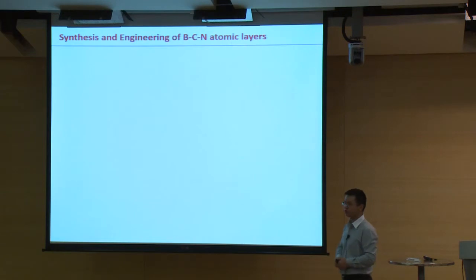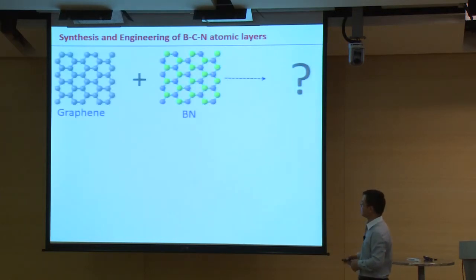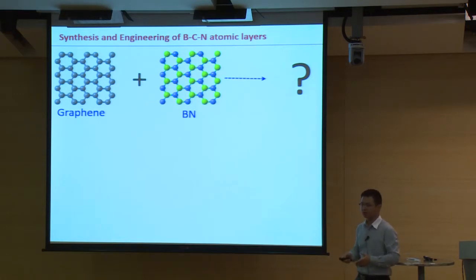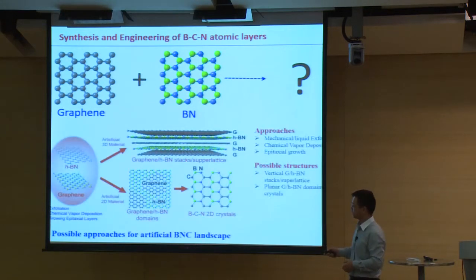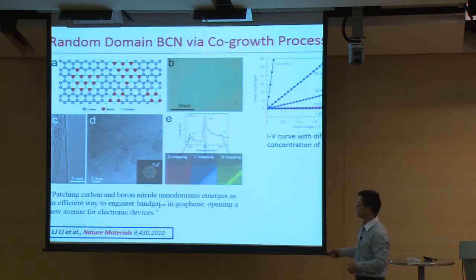Okay, so we move to the BCN system, the ternary system, consisting of graphene and boron nitride. So what will happen if graphene meets boron nitride? What the BCN ternary system looks like, I just mentioned, we have two ways to make them as artificial layers. We can stack them, or we can stitch them into planar structures. And this is an old story we did 3 years ago. We introduced the boron nitride sources and the carbon sources to the furnace. And then we can get the BCN atomic film like this.